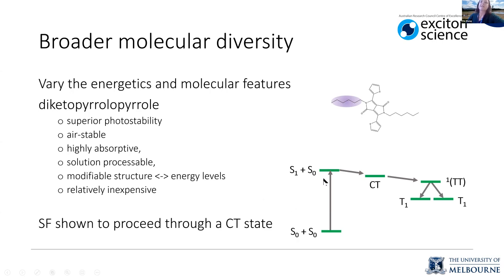And we know that it has this energy level structure where the triplet energy is roughly half of the singlet. And it's been shown to undergo singlet fission in thin films, and that happens through a charge transfer state. So it's kind of interesting to look at.